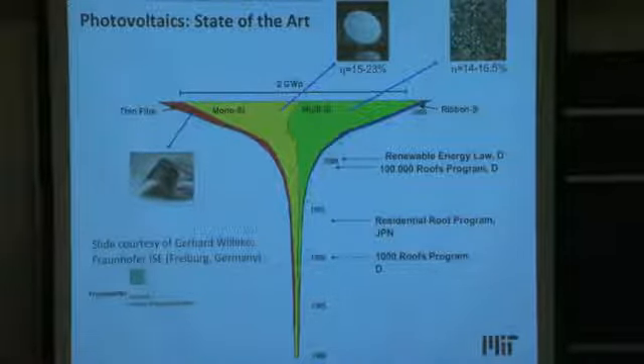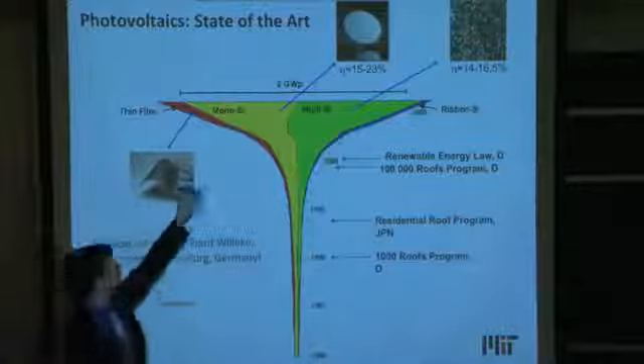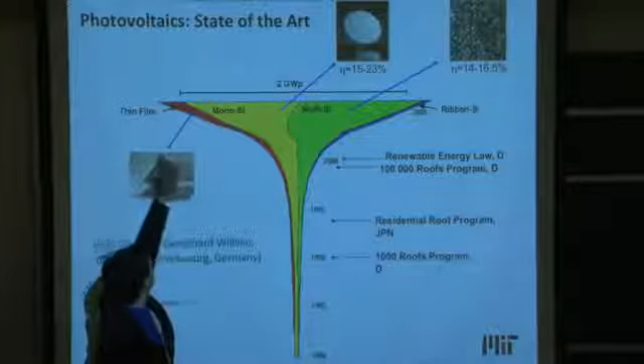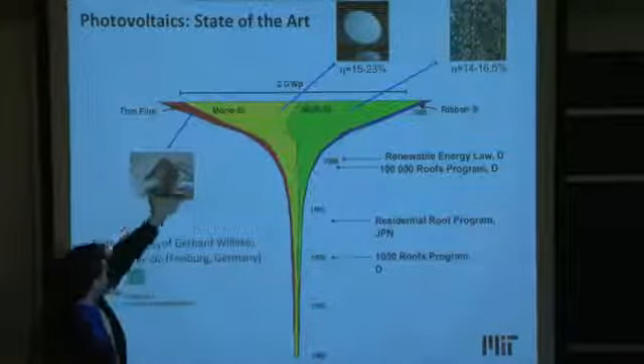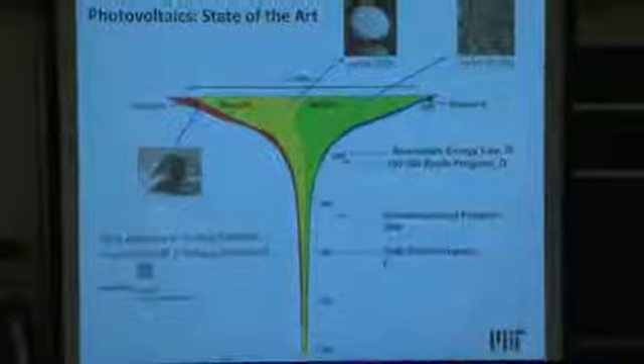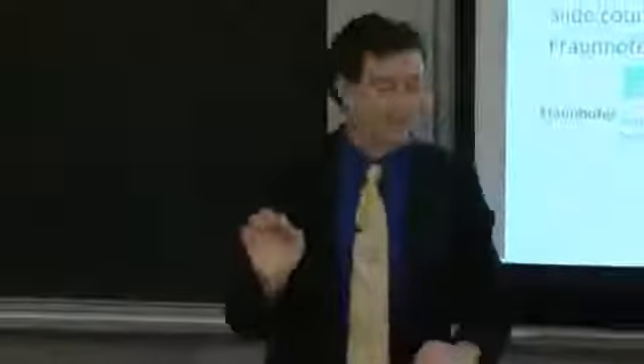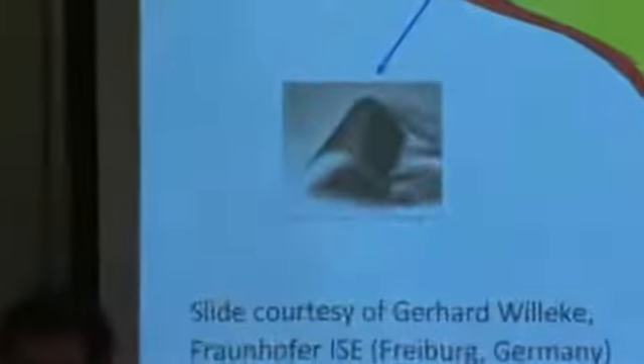Now let's go piece by piece. What is monocrystalline silicon, multicrystalline silicon, and thin films? Well, thin films are materials that are usually between a few hundred nanometers up to about 3, maybe 5 microns thick. To give you a size perspective, your hair is about 50 microns in diameter. So we're talking about 1/50th the width of your hair. That's the active absorber layer. And of course, the plastics and encapsulants and everything else that go around them make it a bit thicker. But the absorber layer is very thin, and so you're not spending much on your absorber layer.